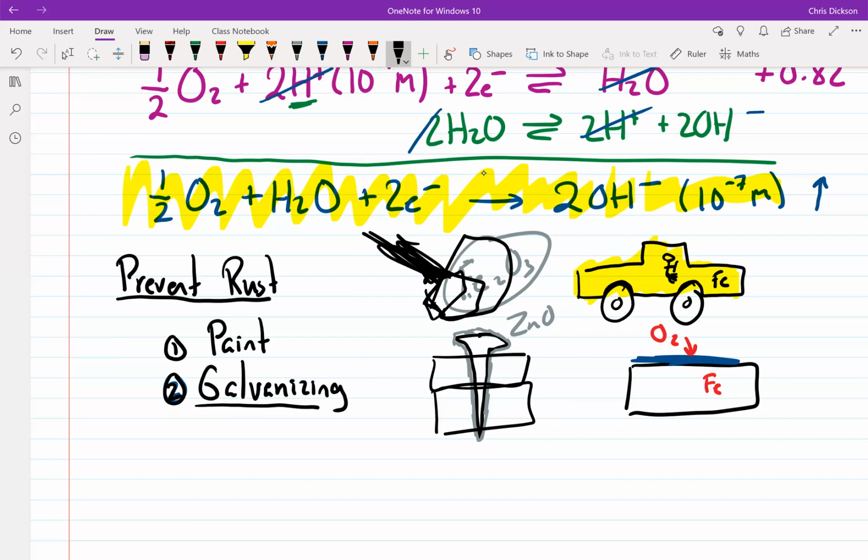And of course, if you hit the top of a nail with a hammer, big metal hammer, you can chip parts of the zinc oxide layer off. And that's actually the most vulnerable part of the nail now. And over time, rainwater would get in there and corrode the nail from inside. And then, of course, once the nail's corroded, the boards can come apart again. So what's a good idea is to repaint the surface after you're done. So after you nail things together, maybe put a coat of paint on it or some stain on your fence, and that'll help protect it.